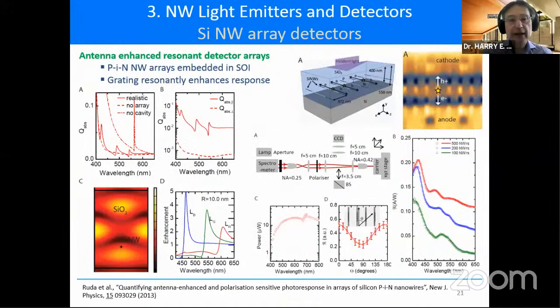The last thing I want to talk about here is this idea that we can also have wires that are not independent from each other but dependent, and they form a collective response. So the movement of charges in one wire effectively affects the field, sort of like a dipole interaction of adjacent wires and so forth, and rather like a photonic crystal, and we'll talk about that in a second, we can form a grating type cavity structure where the overall structure has resonances with higher Qs. And we did this in the case of silicon PIN structures, so now we're looking at separate absorption and gain type structures that people use for PIN type photodetectors, and these can be used for single photon counting as well, by the way.